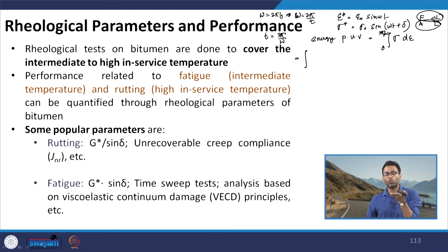So if you consider one point in the pavement, the wheel will come here, it will go. So this point is stressed for a particular time and then there is a rest period. So if during the rest period my binder is capable of recovering completely, even though the initial deformation be higher, then the rutting resistance will be higher because the accumulation of permanent tensile strain will be lower here.